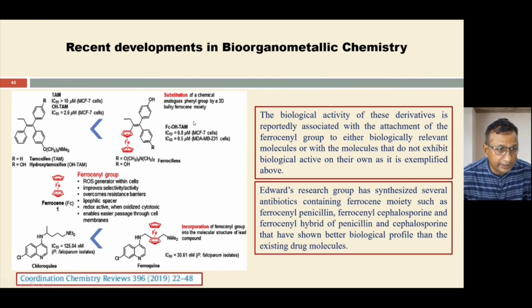As you can see here, tamoxifen is a well-known drug, and the anti-cancer activity of tamoxifen against breast cancer cell line MCF7 is more than 10 micromolar IC50, that is 50% inhibitory concentration. But after the incorporation of the ferrocenyl group into the structure of tamoxifen, that gave us ferrocifen, the activity of this ferrocifen against the same cell line is found to be almost 10 times better than tamoxifen, right? So you can just see how the biological profile of a well-known drug can be further increased simply by incorporating the ferrocenyl group into the structure of that drug.